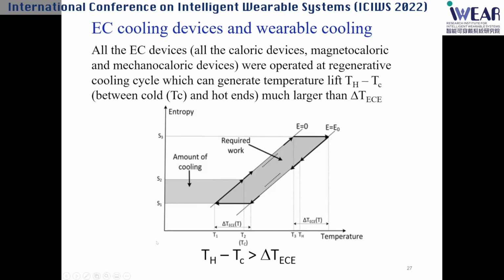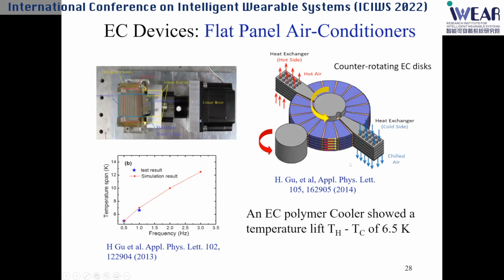So we did a very simple study. This was in 2013 and 2014 for the EC polymers, and we call it a flat panel air conditioner. Basically, this is a very flat design. You have counter-rotating EC discs, one rotating in one direction, another in the clockwise direction. The thickness could be about 1 centimeter, and the size could be 10 centimeters. And the cooling side is half a centimeter. But what we find here is the maximum temperature span between hot and cold end is only about 6.5 Kelvin. At that time, this was really the highest among all these devices.